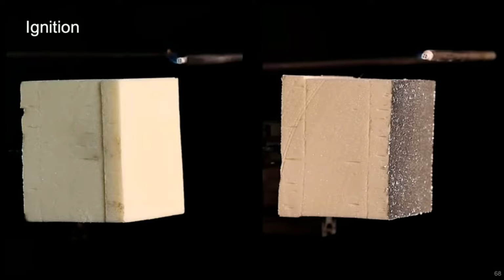And yet, its influence on the reaction to fire behavior is profound. We will see the formation of bubbles behind the foil facer. This is an indication of the generation of pyrolysis products from the PIR foam behind the foil, and those pyrolysis products are unable to escape, thus preventing their mixing with oxygen and their burning. So I'll now let it run, again, stopping periodically.